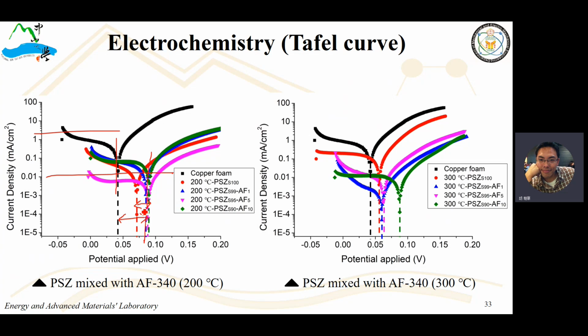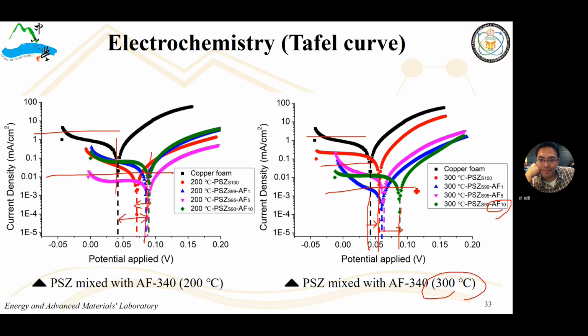Okay, and then if we look at the higher cross-linking temperature, what's going to happen? You see, for the 300 cross-link temperature, if we desire to get the higher corrosion potential and the lowest corrosion current, we need the higher content of the fluorinated resin, right? This is the pure copper, and the red one is the copper foam coated with the pure precursor, and this one is the 10% weight of the fluorinated compound, right? And this potential increases, and the current is reduced, okay.